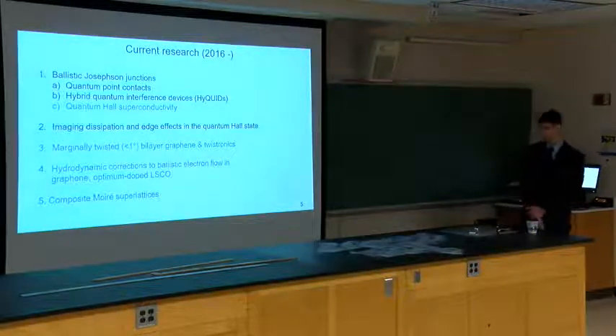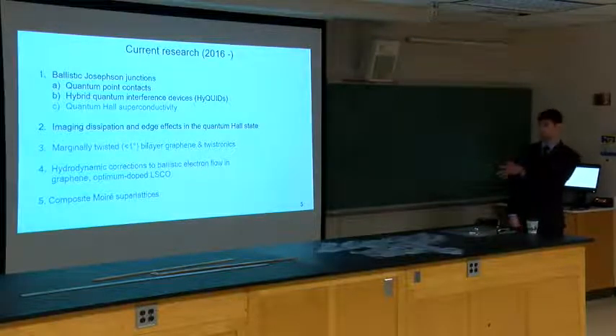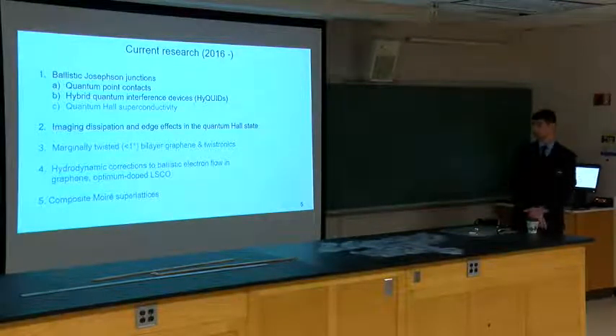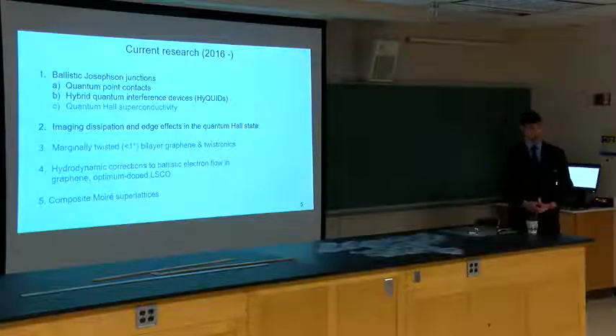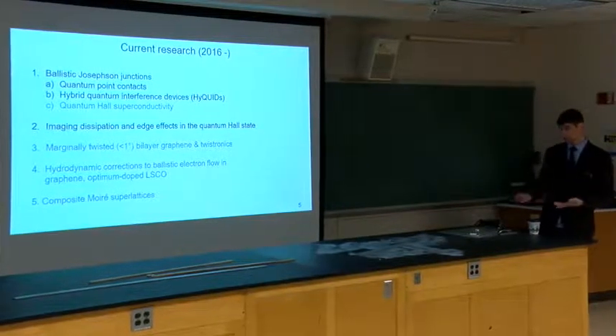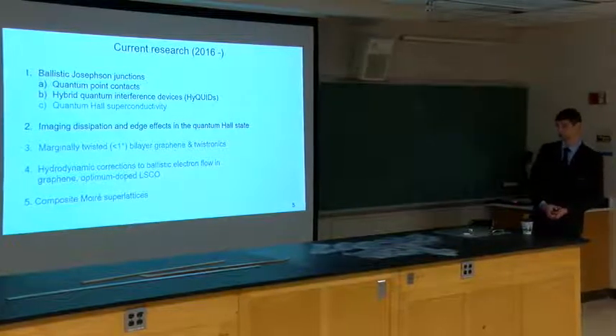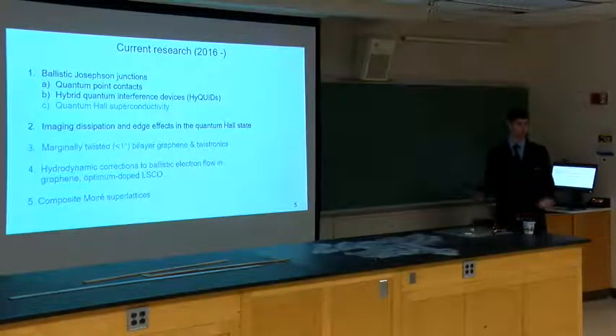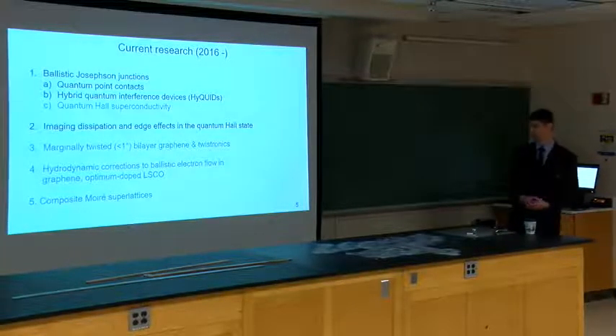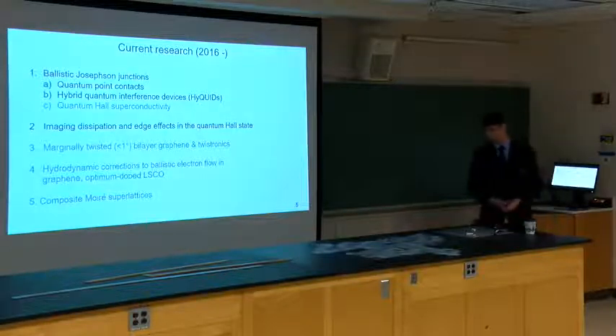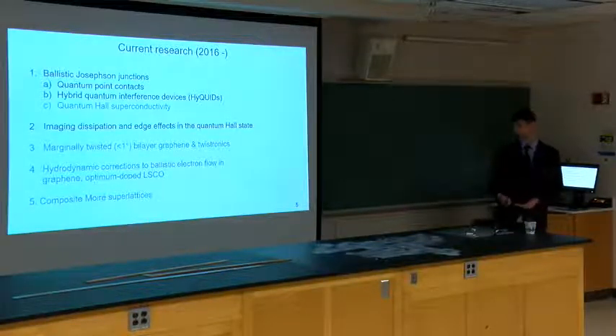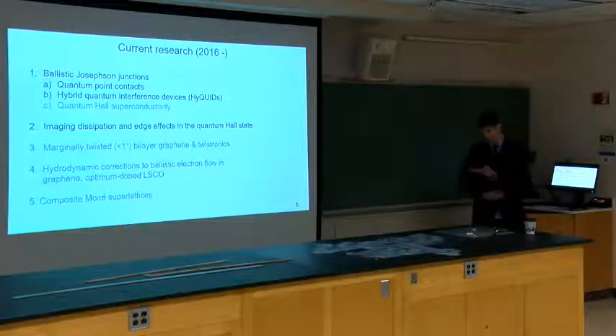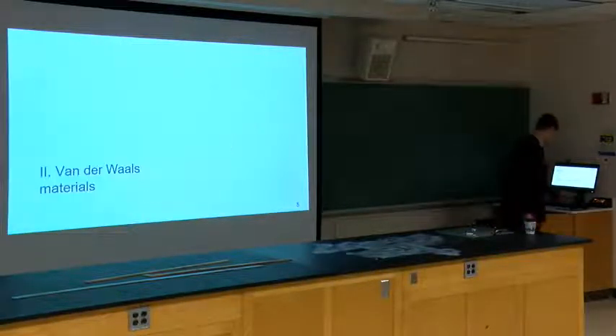So my current research, of which I'm only going to talk about the black colored topics, works with superconducting devices made from 2D materials, then imaging dissipation and edge effects in the quantum Hall state. But I've also worked significantly, especially recently, on marginally twisted bilayer graphene and the so-called twistronics or engineering flat bands in graphene, as well as some other quite different projects such as hydrodynamic corrections in optimum doped lanthanum strontium cuprate, which is still ongoing, or other twistronics like composite Moire superlattices.